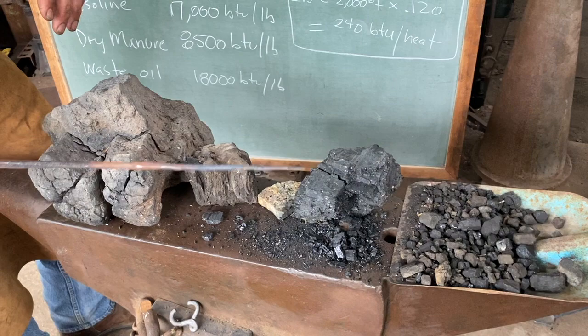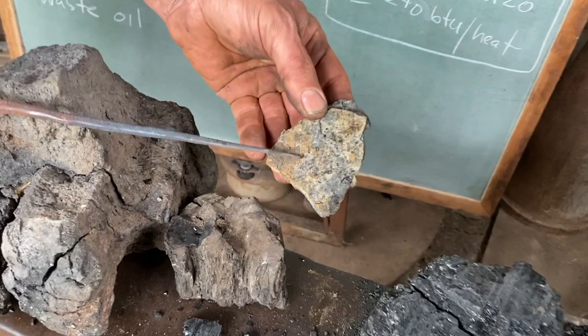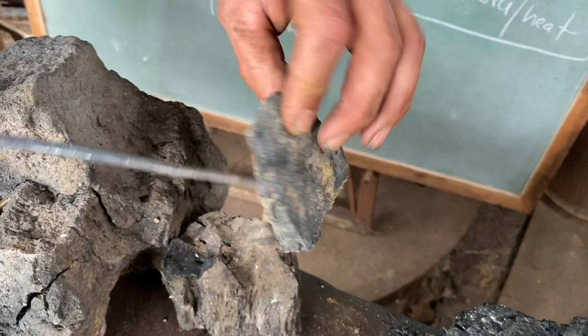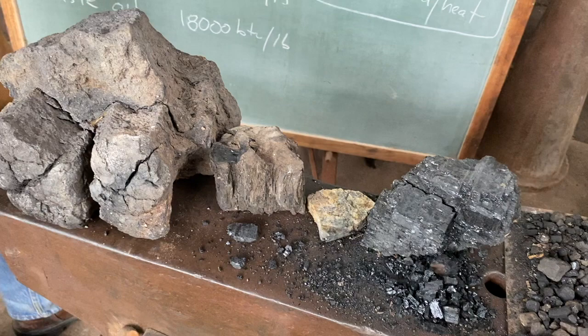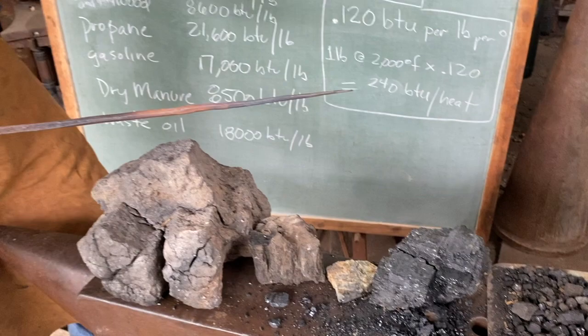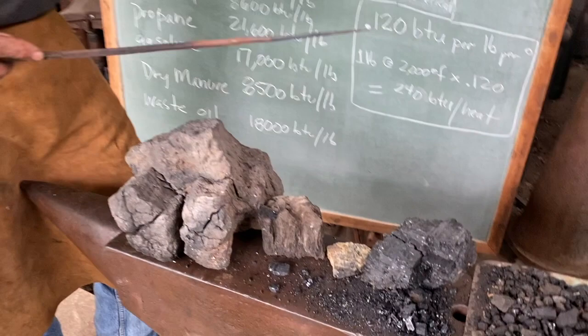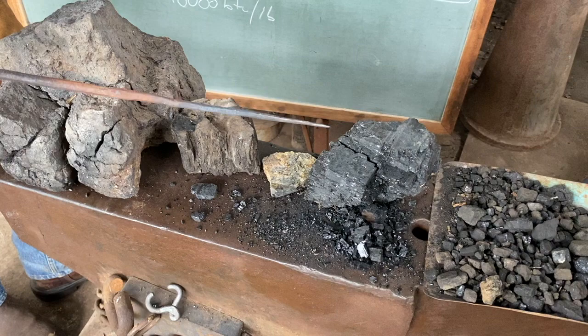Now, coal that you want to avoid is coal that has quite a bit of sulfur in it. And you can see the sulfur in this, the yellowish color. So this is coal, but that coal has a lot of sulfur, and that sulfur will be absorbed into your hot steel. Hot steel is like a sponge. It absorbs elements from the atmosphere. So it absorbs oxygen, hydrogen, sulfur, phosphorus, and these things are deleterious to the quality of your forging. So you want to be really careful about making sure that you have the best quality coal that's available within your budget.